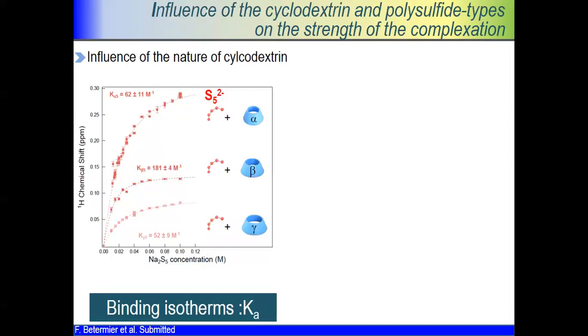And what we are looking at, we are measuring on the y-axis the chemical shift as a function of the concentration of this S5 minus polysulfide. And we found that the association constant is the greatest by and large for beta cyclodextrin, which is in the middle, which means that this is the cyclodextrin which has the most affinity for this polysulfide.